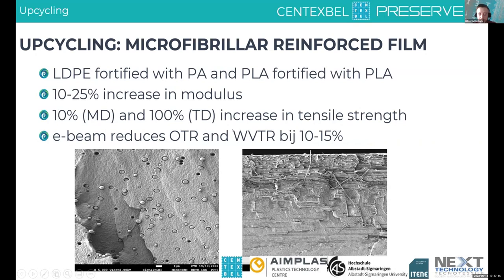By optimizing the extrusion process, we're able to generate, as you can see in the images, some microfibrillar structures where you have a bulk of polyethylene and microfibrils of polyamide inside of this bulk material. The creation of these microfibrils actually improves the properties of the bulk polyethylene. So the modulus increases by 10 to 25%, and the tensile strength can increase up to 10 or even 100% by blending these materials and using the right additives.